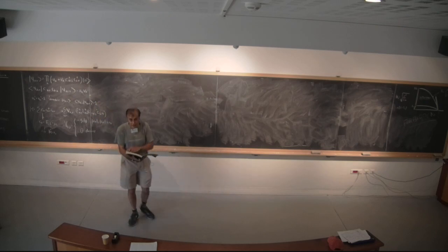They chose it to be, as I mentioned before, equal to minus G0 over V for electrons near the Fermi surface, and 0 otherwise. In other words, this only acted on electrons very, very close to the Fermi energy. And the picture that we had before, here is the Fermi surface, and now this can be any set of pairs.